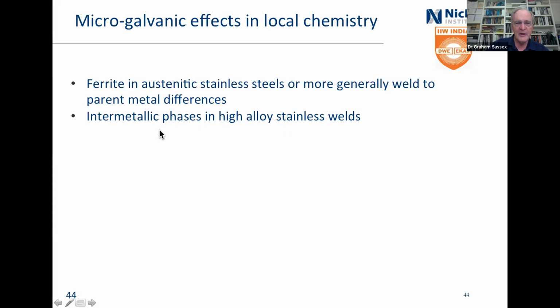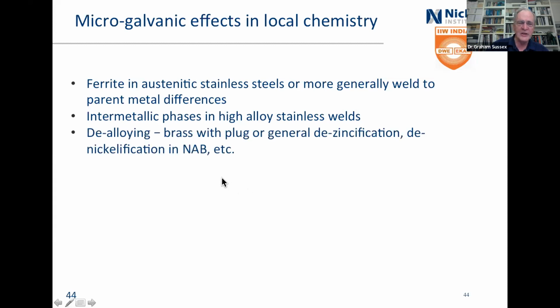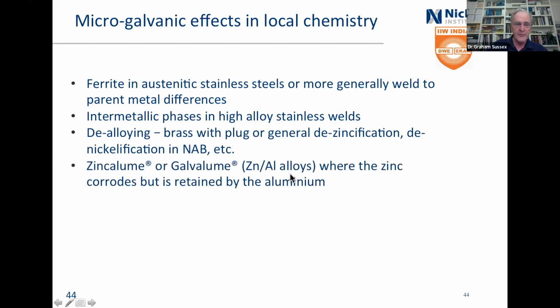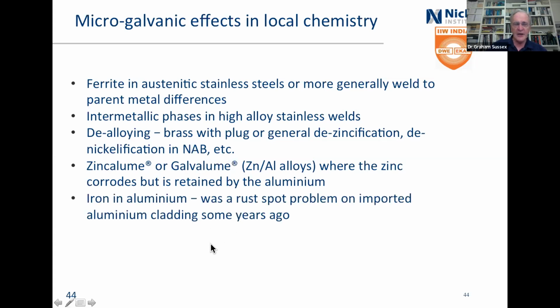in the galvanic effect. Intermetallic phases in high alloy stainless welds, de-alloying with denickelification, or the plug or general dezincification if you've got people who haven't put the arsenic in, or they haven't heat treated it. And the zinc aluminium galvalume, the zinc aluminium alloys where the zinc corrodes, but it's retained by the aluminium. So that works. And these work basically for roofs. This is Australia, that's the States. And iron and aluminium. Well, that's bad news, but it's nothing to do with welding. There was a rust spot problem there. There was rogue iron in some out of a major supplier.